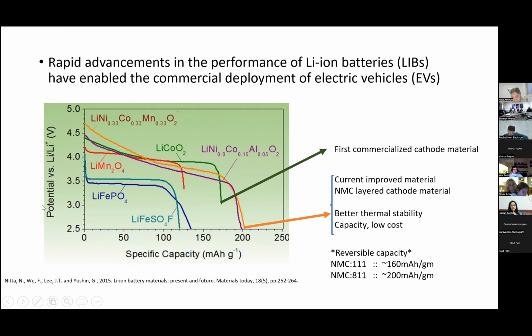So further, what happened was, as you see here, the green curve, lithium cobalt oxide, some percentage of the cobalt is replaced or substituted with nickel or manganese. When they replaced some percentage with nickel and manganese, they saw higher voltage stability of these materials. And not only that, they observed an increase in the lithium-ion storage capability in these materials. It is because of the redox ability of the cathode elements, like nickel and manganese.